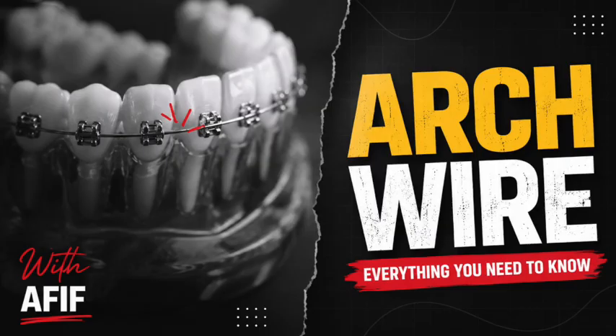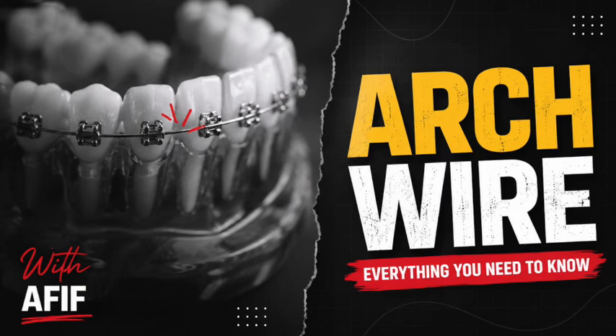It really is. And the specific thermodynamics of this process have been beautifully detailed in the orthodontic literature. They rigorously explored what is called the temperature transition range, or TTR. Okay, TTR. The true genius of modern metallurgy is how manufacturers have learned to hack this transition temperature. How? They don't just use standard nitinol anymore. They add copper to the alloy, creating what is known as copper nitinol. Copper. By meticulously tweaking the percentage of copper, they can precisely dial in the transition temperature to match exact human body temperature. Oh, wow. So they are customizing the chemistry of the alloy. So the wake-up point, the shift from martensite to austenite, happens exactly at 98.6 degrees Fahrenheit. Exactly. They tuned it perfectly to the human body. That is insane. It's amazing.